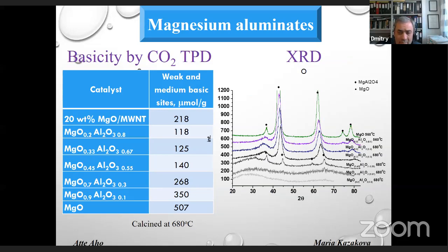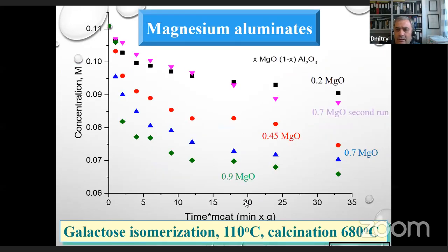In order to overcome the problems of leaching, we used other types of materials which are known to be more stable, such as magnesium aluminates. The catalysts were prepared by Maria Kazakova in Novosibirsk. So we had materials with different ratios between magnesia and alumina, and with different amounts of weak and medium basic sites. All of the materials were calcined at 680 degrees C.